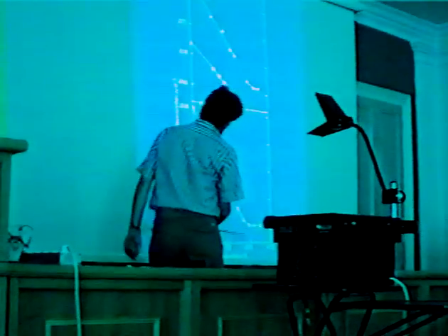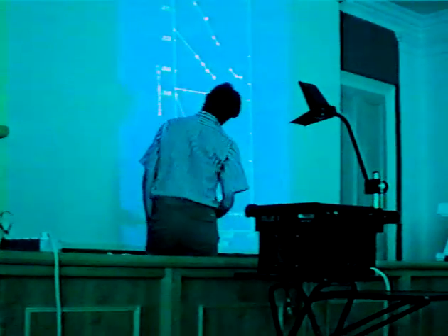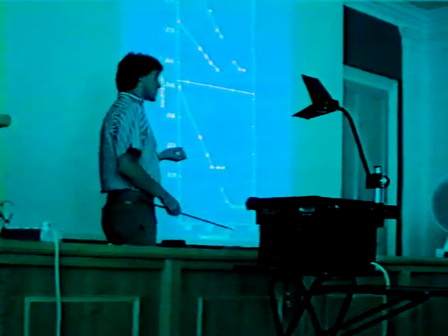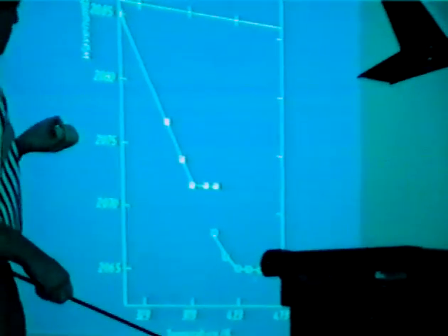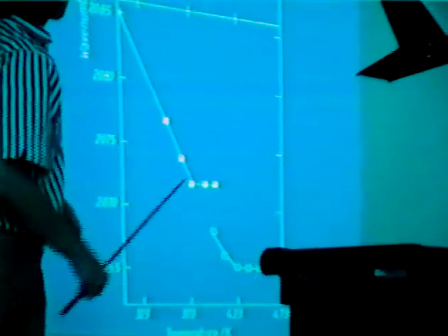We look first of all at the catalyst prepared by the stepwise, sequential impregnation sequence. And in the case of the fresh catalyst, again we see invariance in the carbonyl stretching frequency, again 2064 wave numbers, indicating that we've essentially got something that's very similar to the platinum catalyst on its own. And as we saw for platinum, if we then re-reduce this in CO, then again we see a shift to higher frequencies during invariance, but we still have invariance in the stretching frequency of the carbonyl. So we still have either platinum-only particles, or at least sufficiently large ensembles of platinum within the platinum-rhodium crystallites.